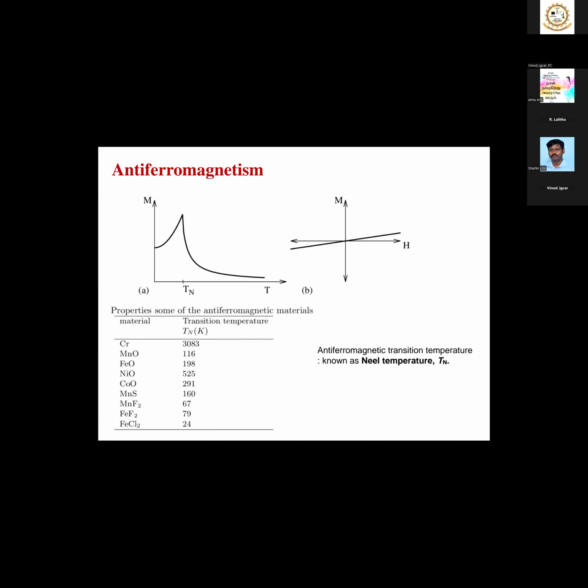And this will be the response for antiferromagnetism. See here, below the transition temperature TN, known as the Néel temperature, antiferromagnetic ordering starts. In antiferromagnetism, that ordering will be opposite, so magnetization should fall. That's why it is falling. For a single crystal, perfectly aligned antiferromagnet at T equal to 0, all the moments are aligned antiferromagnetically, which means the moment should be 0. But generally for polycrystalline samples, random crystallographic directions will be there, so that's why it will not go exactly to 0. Some examples of these materials are also there.